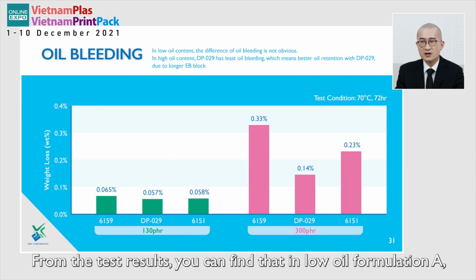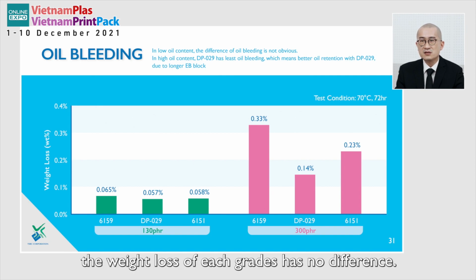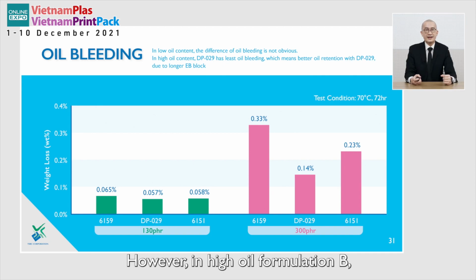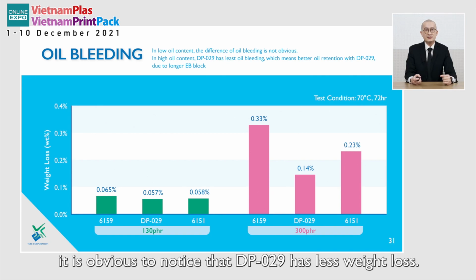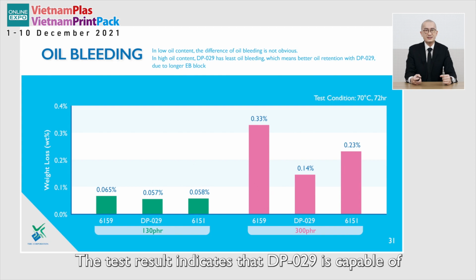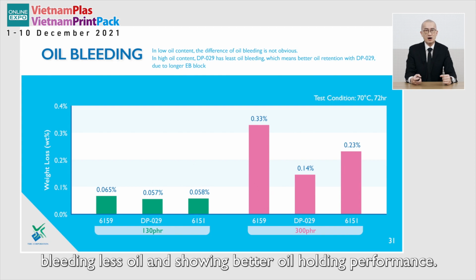From the test result, you can find that in low oil formulation A, the weight loss of each grade has no differences. However, in high oil formulation B, it is obvious to notice that DP029 has less weight loss. The test result indicates that DP029 is capable of bleeding less oil and showing better oil holding performance.